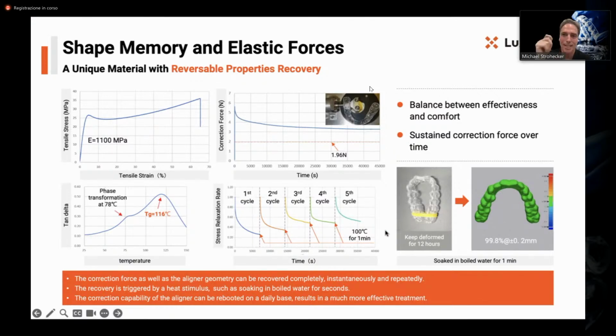You take a thermoform aligner in and out of your mouth, and that will deform, and be less and less efficient. So you have accuracy going against thermoforming. Now you're taking it in and out of your mouth, and that's weakening or opening it up a little bit, so its accuracy is even worse. With the direct print, you can produce it more accurately, and then every time they disinfect it with hot water, it goes right back to shape. This has never been done before.